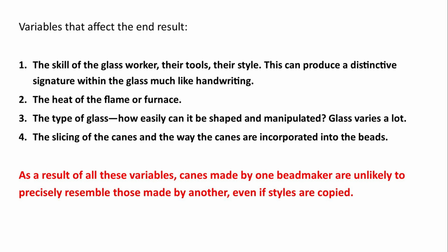My study of millefiori mosaic beads has shown that these beads have much to reveal when the different cane slices are analysed. Cane making is one of the most difficult techniques of glass bead making, and many variables affect the end result. The skill of the glass worker, their tools, and their style. This can produce a distinctive signature within the glass, much like handwriting. The heat of the flame or furnace, the type of glass, how easily it can be shaped and manipulated. Glass varies a lot. The slicing of the canes and the way the canes are incorporated into the beads.